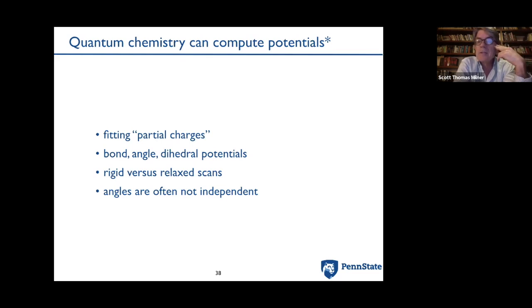So how do you get those? Well, that's where the blood and sweat and toil of countless graduate students comes in, because remember how the potential we're using is called OPLS, optimized potentials for liquid simulations. Somebody optimized those, and a lot of what they optimized were the attractive interactions in order to get the densities and cohesive energy densities and boiling points and stuff like that of a whole series, hundreds of organic liquids.